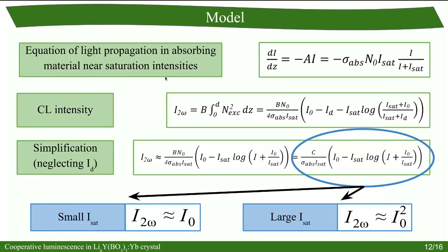After that, we have to solve the equation of light propagation in this absorption material near the saturation intensities. So that means that in the equation of light propagation, the absorption coefficient changes with the intensity, and for the cooperative luminescence intensity, we have to calculate this integration, which can be done using this equation, and we get a function, which can be seen here. In this equation we can see that there is the intensity I0, which is the illuminated laser intensity. The intensity I_D is the intensity at the exit side of the sample, and these are geometric constants, and the ytterbium ion concentration. This is the absorption coefficient, and I_sat is the saturation intensity.